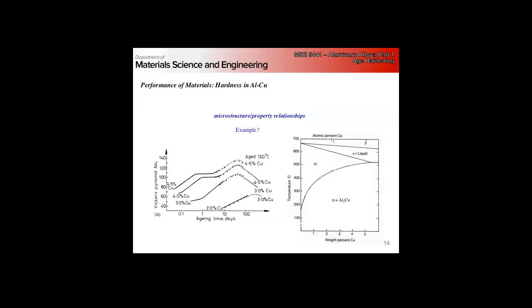The main thing is, what's the main general trend here? So just think about this, the 4%. In general, the general idea is you're going to have GP zones followed by the other phases of interest. And if you get a nice dispersion of GP zones, those are natural places for your intermediate phases to grow, right? I don't want to speculate and say exactly what's happening. I haven't looked at enough micrographs of low concentration counters. I'll say something stupid if I just open my mouth.